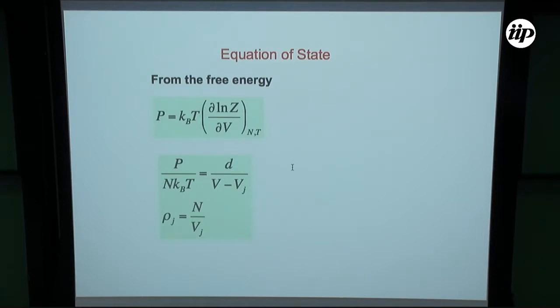From the free energy, one can get the equation of state. For the equation of state, I take a derivative of log Z with respect to volume, and it gives this expression. So you can see that the pressure diverges when v reaches this v_j. v_j is related to the jamming density in this way. So this equation of state predicts some sort of jamming transition at P infinity.